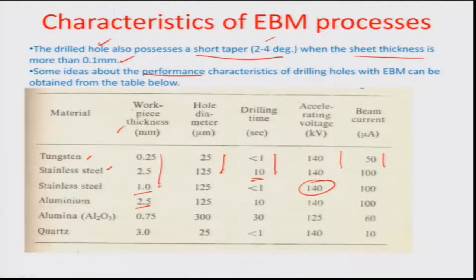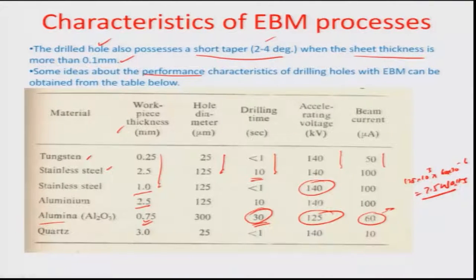So a material like alumina, for example, which is very, very hard, can be cut with a higher drilling time. Okay, so 0.75 mm workpiece thickness is cut in about 30 seconds, and there you apply a beam current of 60 microamperes and an accelerating voltage of 125 kV, which makes it about how many watts. We can just check this. So 125 times 10 to the power of 3 times 60 times 10 to the power of minus 6. So this makes about 7.5 watts of power. So this is reasonably good power that you are using for cutting a small 0.75 mm or 750 microns thick alumina workpiece. So that is how you can characterize the various performance related parameters with respect to the beam process.